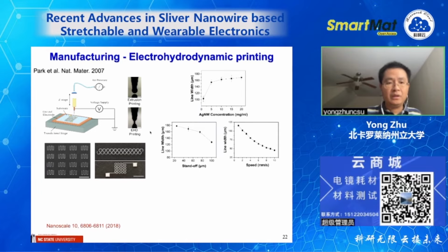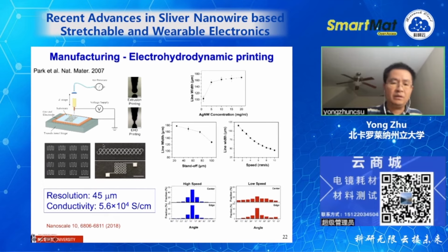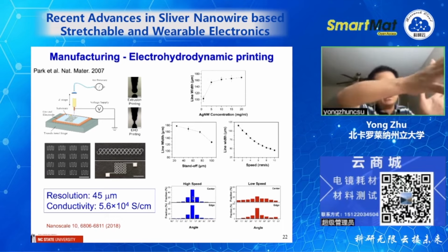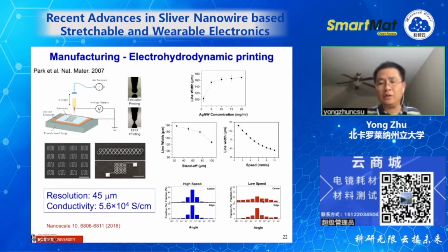So we were able to print with a resolution of about 45 micrometers, and the conductivity is also very high, a very high conductivity for a stretchable electrode. We did careful studies, looking at the effect of different printing parameters, including concentration and speed. Quite interestingly, probably not surprising, at low speed the center is reasonably aligned but the edges are not. For the high speed, the center of course is still aligned, but the edge is also better aligned. That's not surprising, but it can be helpful.